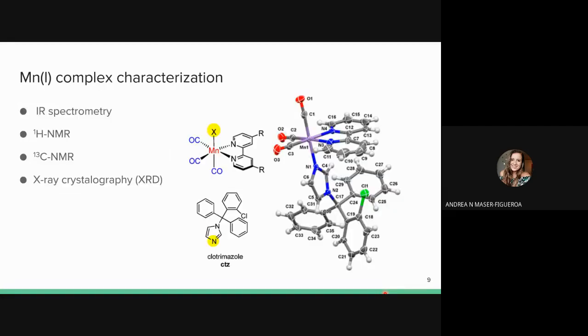They characterized the complexes via infrared spectrometry. They identified the characteristic 3-carbonyl stretching bands. They also used HNMR and CNMR, and they indicate that they did observe the symmetrical bipyridine coordination. Moreover, they used XRD to analyze CTZ, and they identified that the manganese atom is in a pseudo-octahedral environment where the moiety is coordinated by the bidentate bipyridine ligand in a symmetrical way, and that the azole ligand was bound by the imidazole N1 atom.